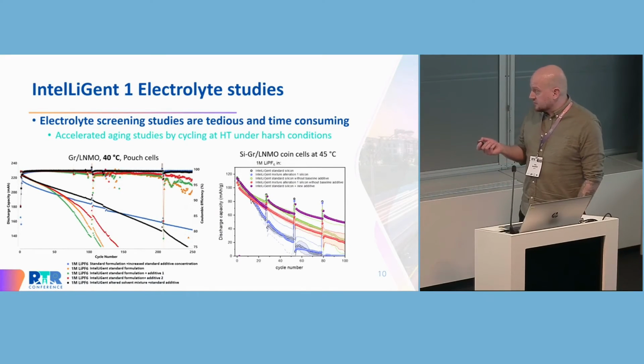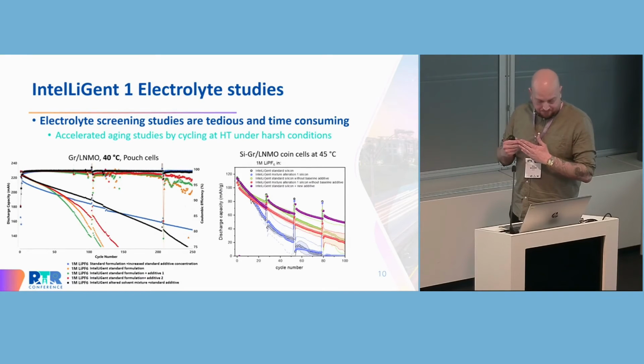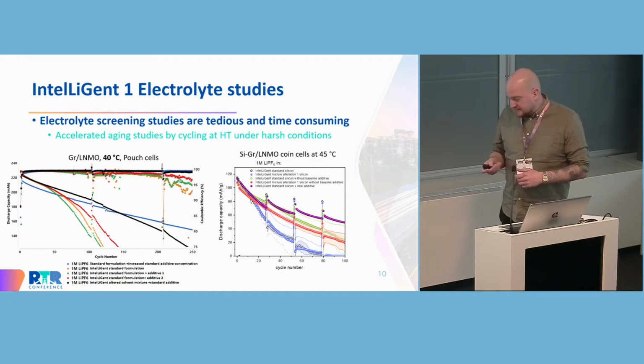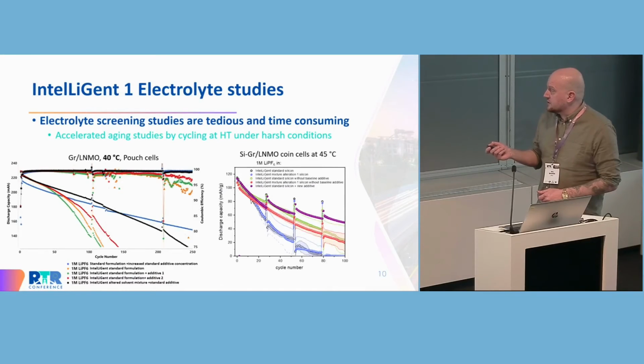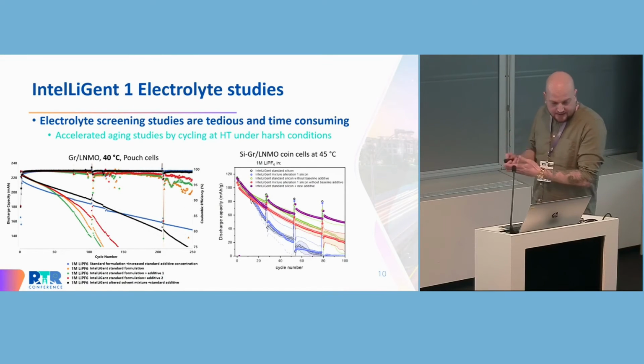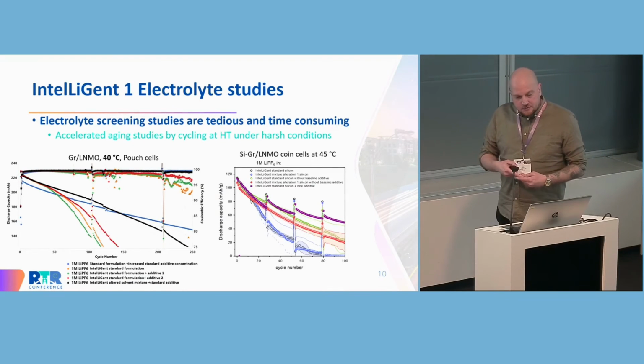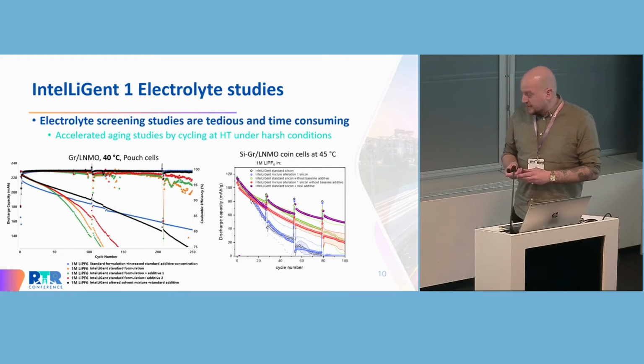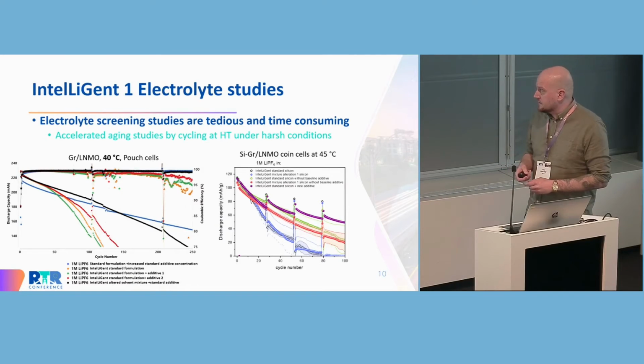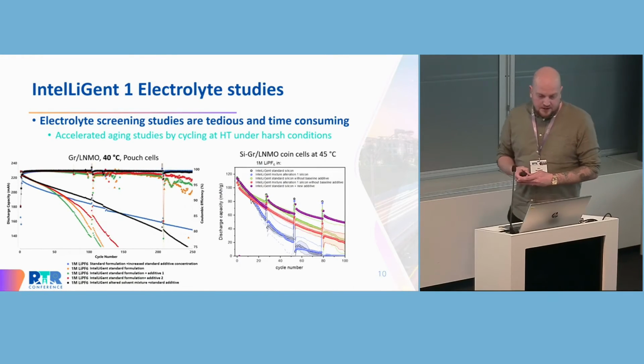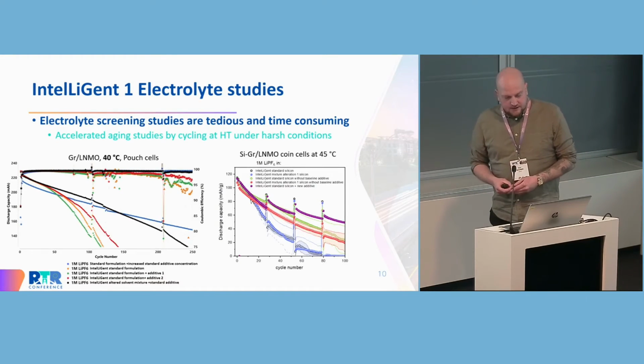It just shows you there's a lot of resistance building up in the cell, because you can see whenever we switch the current to a lower current, the cell actually still has capacity, but the resistance in the cell is so high that the system can't follow. But also here we already have some interesting contenders, like in purple. We defined some new additives that we can add to the system that drastically increase the cycle life.